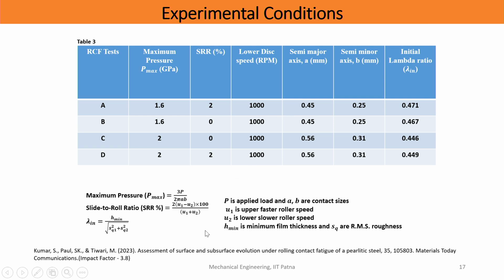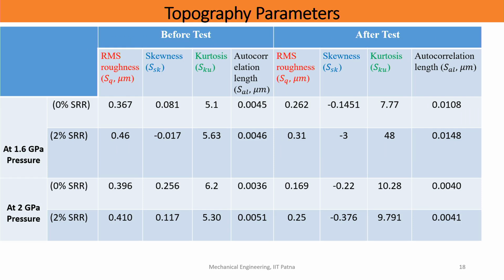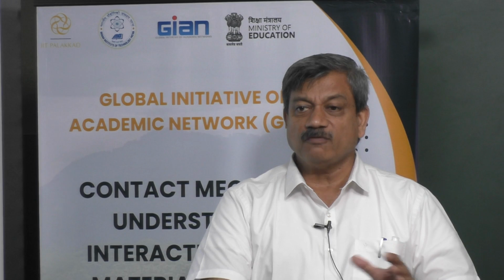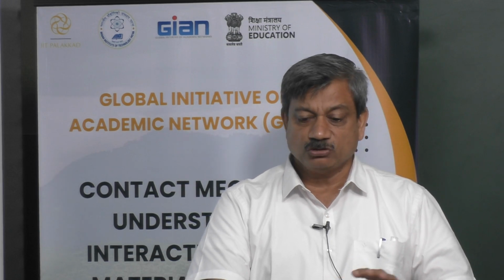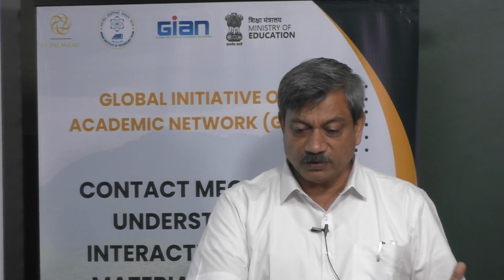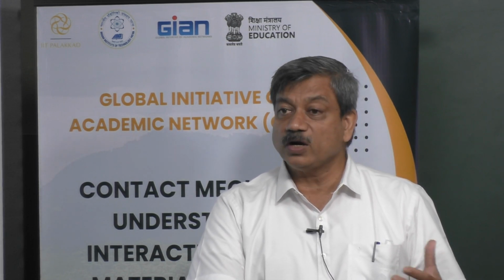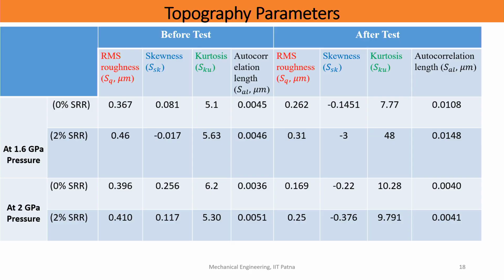So, this is how, these are the conditions under which we have done the test, and these tests take a long time. The other thing we have tried to measure is the surface topography parameters before and after the test. So, what are the surface topography parameters? Skewness, kurtosis of the surface roughness, then autocorrelation length. We are talking about 3D surface roughness here now.